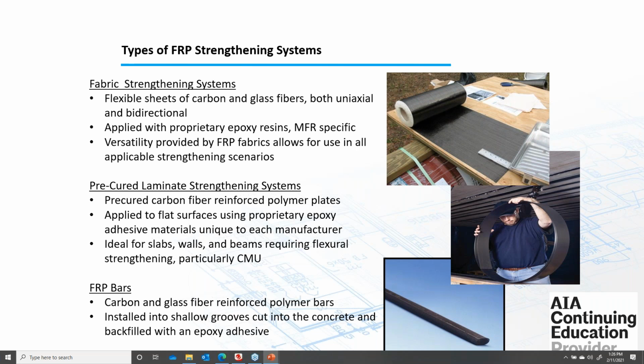The fibers are running parallel with that ruler, so it just runs along the length of the sheet. With the biaxial, bidirectional fabrics, they'll either be running at plus or minus 45 degrees, so they'll be at an angle, or some of them are 0, 90. It really just depends on the manufacturer. They'll specify whether it's 0 or 90 or plus or minus 45 degree fabric.